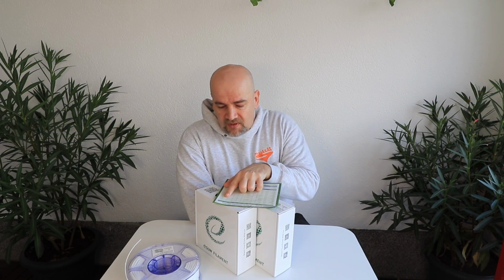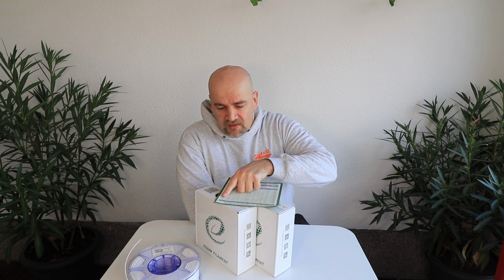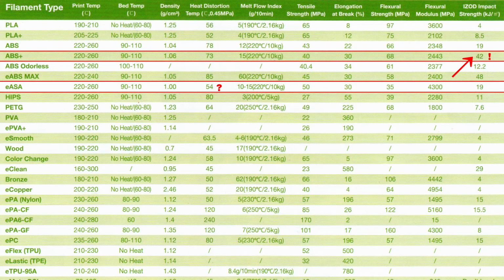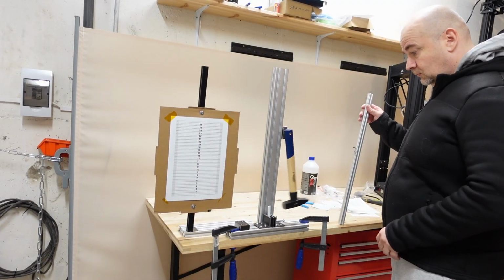Another very big difference is in the izod impact strength. The ABS Plus has approximately twice the strength. And actually this may be true, because in my izod impact test, this was the first time that the test specimens didn't break under a half kilogram hammer. But of course we will see, because I will now compare these two materials.